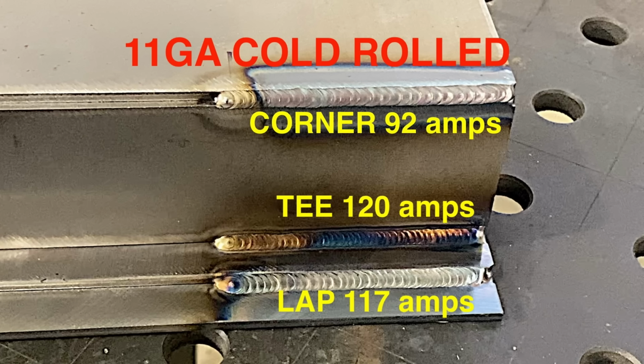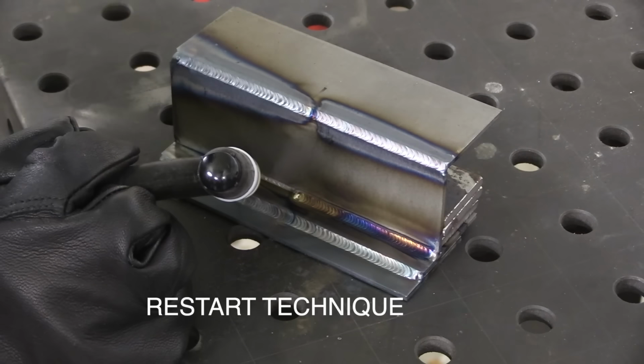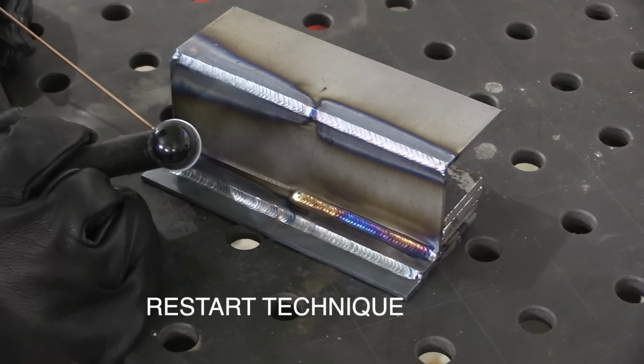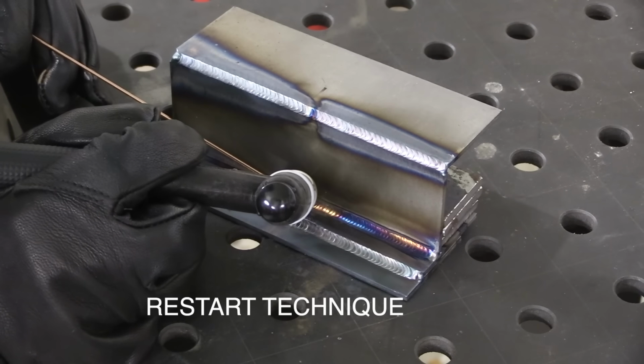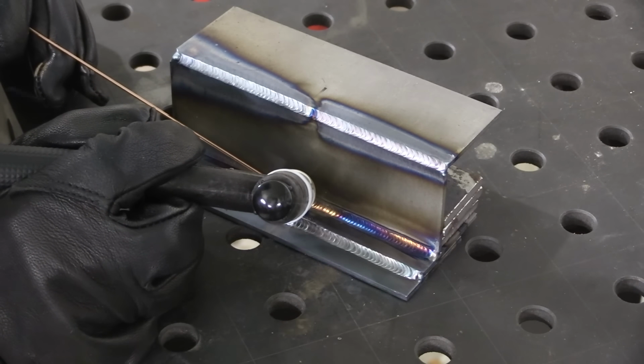You can see that the corner joint only took 92 amps, the lap joint 117, and the T-joint took 120. I didn't actually set the machine exactly that, but I had a camera on the readout while I was welding each of them. It's important to be able to make a good restart. You can stop as many times as you need to if you can make a good restart, and it's also important to have a leak-proof joint.